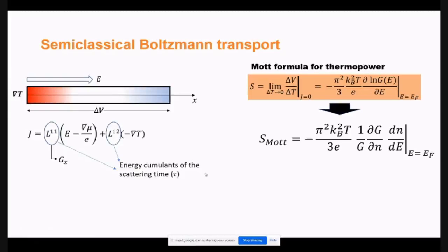And this is what you call the Mott formula, in which the thermoelectric parameter or the Seebeck coefficient is given by the ratio of the potential and the temperature differences, and which, if you look at the final result of it, is a derivative of conductance with respect to energy. Okay, and this essentially is this number. Excuse me. Now, what happens is this number, d log G / d E, can be decomposed into